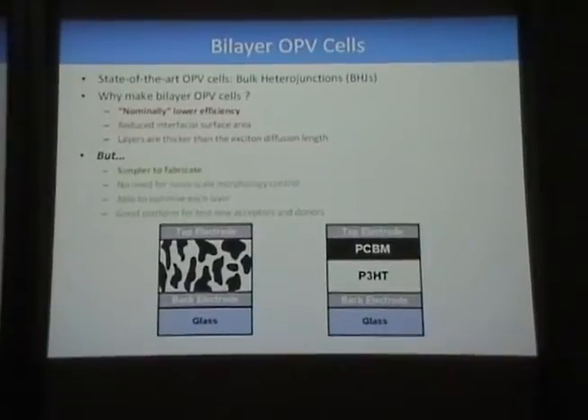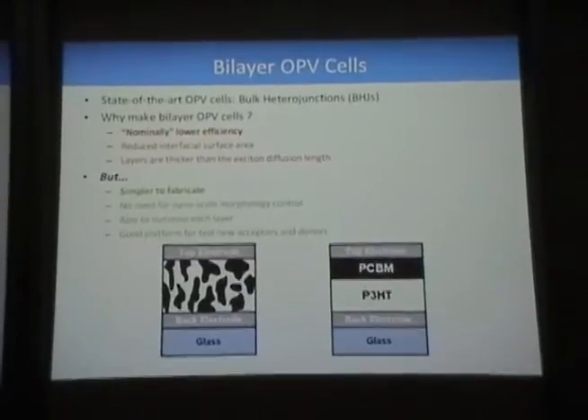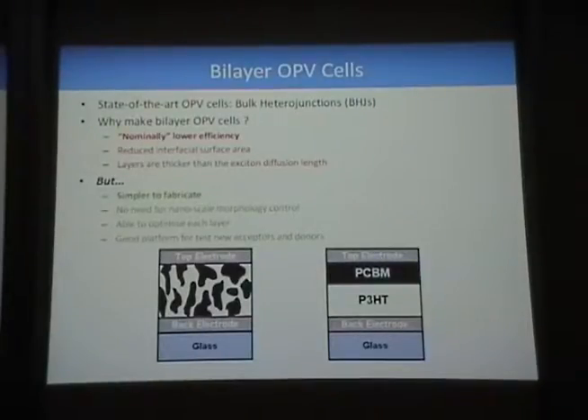So as you are well aware, state-of-the-art technology is the bulk heterojunction solar cell. So the question you might ask is why make bilayer OPV cells? Because they generally have lower efficiency due to the reduced interfacial surface area, and the layers are generally thicker than the exciton diffusion length. However, they are simpler to fabricate. You don't have to worry about the nanoscale morphology control that you encounter in BHJs, and you're able to optimize each layer. And this also represents a good platform to test new acceptor and new donor materials.